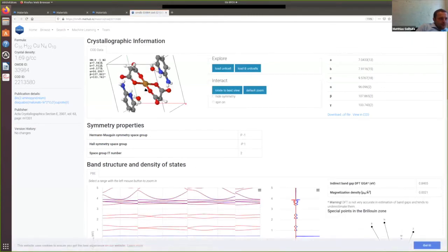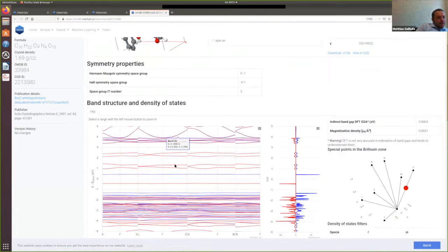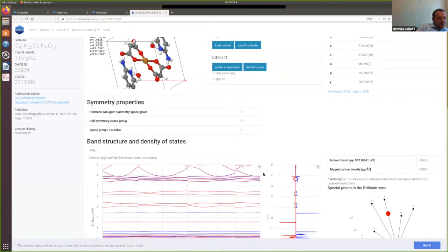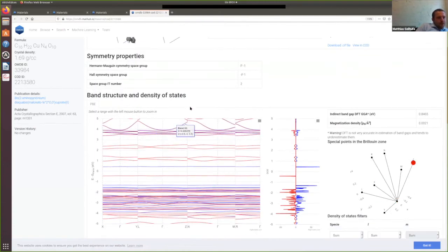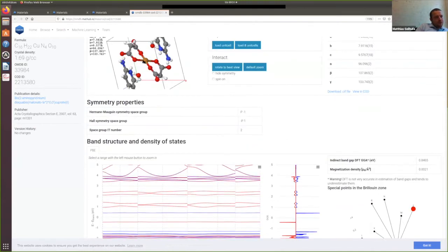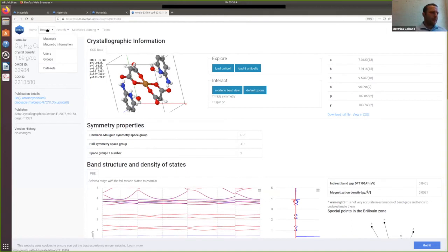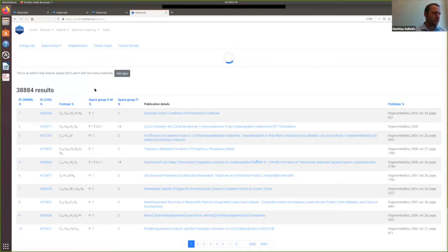And if I take a look at how this comes about, then I can say that in these materials you have atoms with very, very localized electrons. This, for instance, contains copper. Copper has localized d electrons. These localized d electrons also don't want to hop to their neighbors, but what they actually do is get influenced by the surrounding crystal field of the molecular linkers. So they start to split. So the gaps that we observe in this regime are all gaps which arise due to the crystal field splitting of the neighboring atoms. And this crystal field splitting strength is of course much weaker than the 3 eV or something, so that the gap sizes that you expect are pretty consistent.